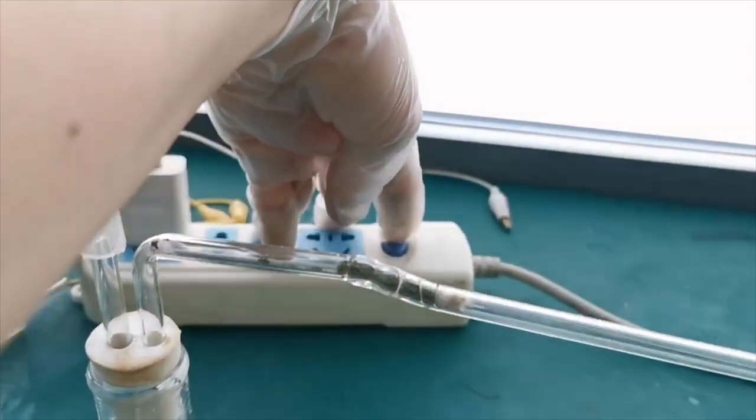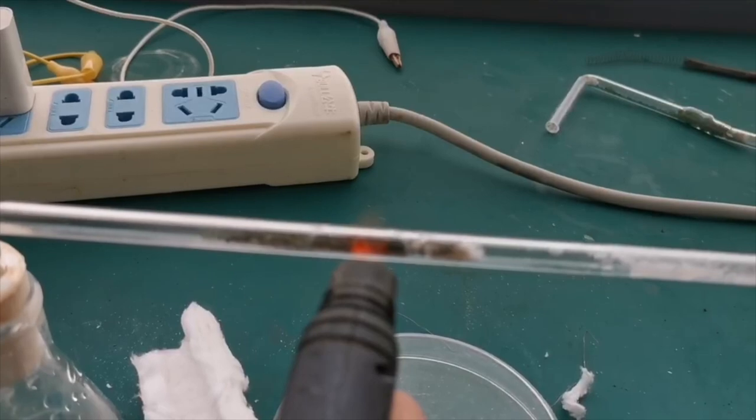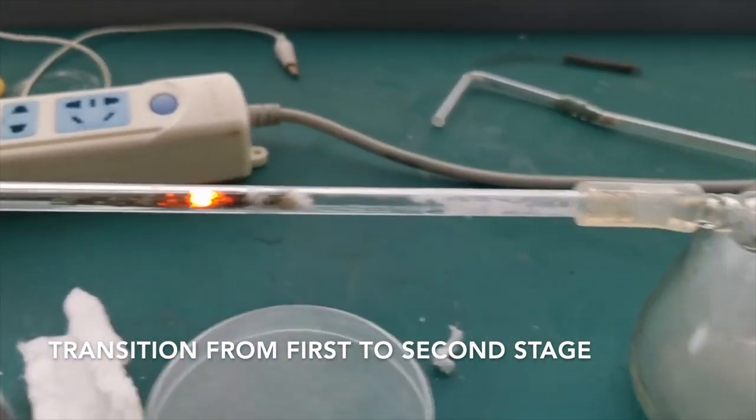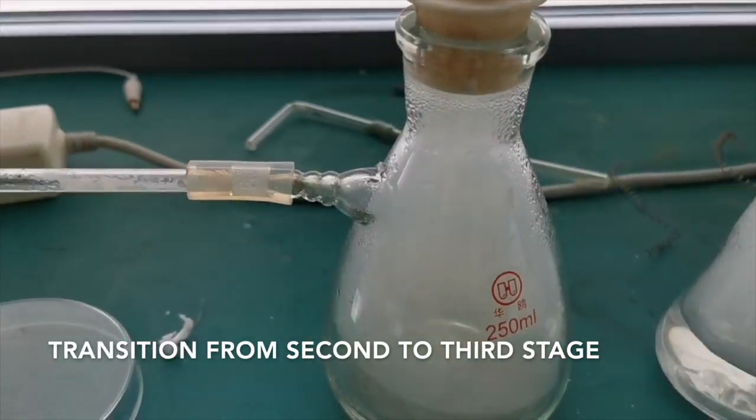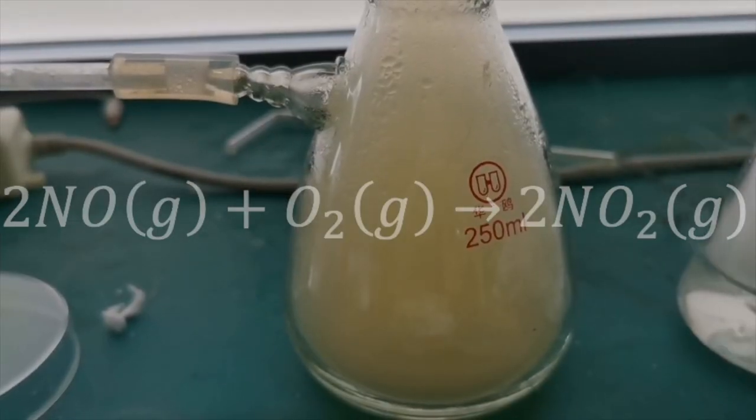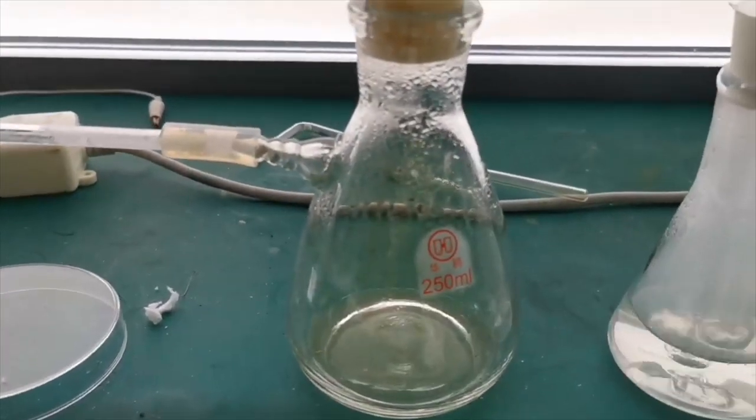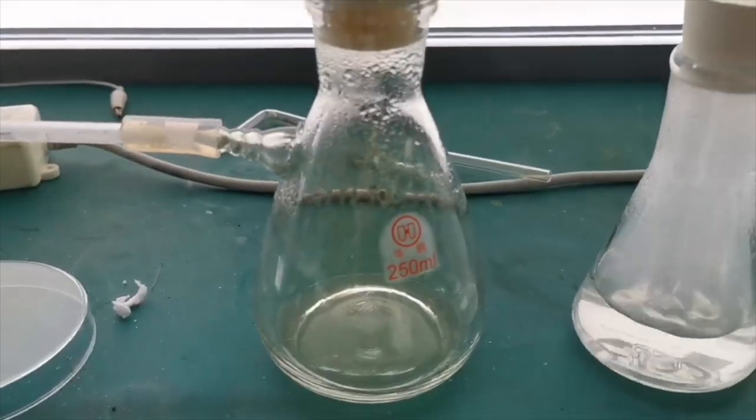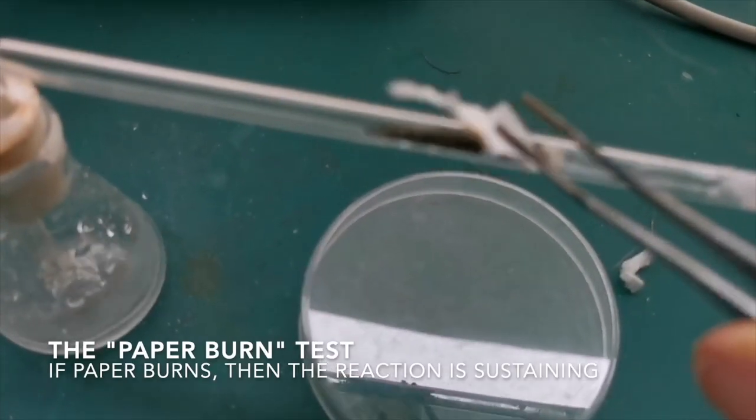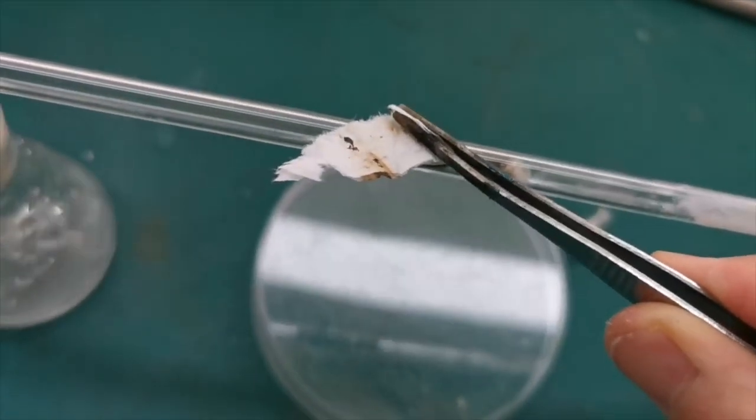The concentrated ammonia allows for a more vigorous and exothermic reaction, which can keep the catalyst extremely hot. A while later, the catalyst only glowed a little bit, but the reaction is still going. To show this, I turn off the pump and the glow disappears. When the gas flow continues, the glow reappears. As I said before, the catalytic oxidation of ammonia releases tremendous amounts of heat and is even able to act as a heat source once it is initiated. Note that the gases in the conical flask were a lot lighter in color and contained a bunch of white fumes. This was the transition from the second stage of the reaction to the third stage, as I call it. I discovered that the reaction takes on three distinct stages.